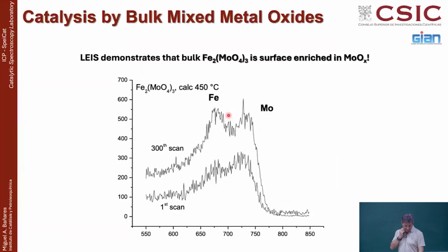And you already saw, according to the low energy ion scattering, that after several scans, and here you have 300 scans, the first sample was essentially moly, but in reality it is iron molybdate. But this is not what the molecule sees. What the molecule sees is essentially molybdenum at the surface.